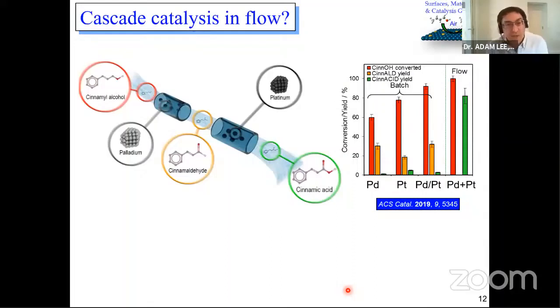You can do the same chemistry in flow, in which case you can have a packed bed of just the palladium catalyst, a second packed bed of the platinum catalyst, and you can flow your reactants through. So the alcohol does the aldehyde transformation over the first reaction, and then you have the aldehyde transforming to the acid over the platinum catalyst.